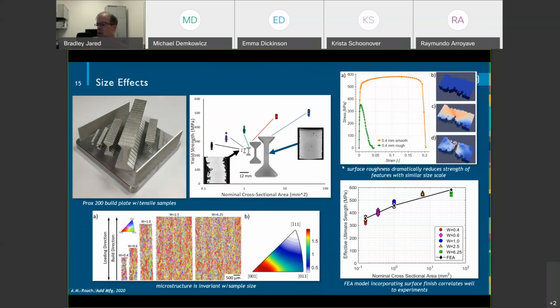That translates to, for the 6 millimeter, really doesn't have an effect. It's really not a big deal. You can kind of think of this as bulk properties. Now, if you start talking about a 400 micron sample, now suddenly 20 microns, if that's Ra, that's effectively peak to valley of maybe 100. Now you're talking about a quarter of your part is actually now essentially a crack. It dramatically reduces the strength properties, and you see that here, right?